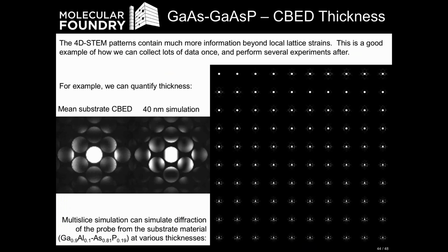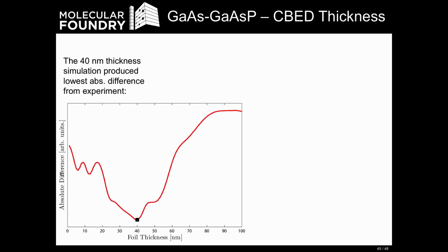And they're not identical. Most of the fine details are pretty good, but there's a couple fall-offs that are a little bit stronger in the simulation than they are in the experiment, probably due to inelastic scattering blurring out the signal a little bit. But overall, if I plot the error, you can see it reaches a pretty strong minimum, the minimum in the mean absolute difference at a thickness of 40 nanometers.